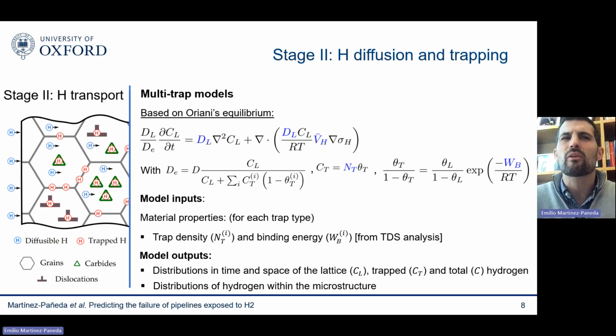So these values, even though there's a bit of uncertainty when it comes to extracting them from TDS analysis, a margin of error of 10, 20%, we don't really care because it's not going to have a role. We don't really care if the steady state is attained in 2 days or 2.5 days. And once you achieve the steady state, it's kind of the same distribution. But once you have these inputs into your material, once you consider this multi-trap model, then you can quantify the distributions in time and space of the lattice, trap, and total hydrogen concentration, and then also, of course, the distribution of hydrogen within the microstructure.